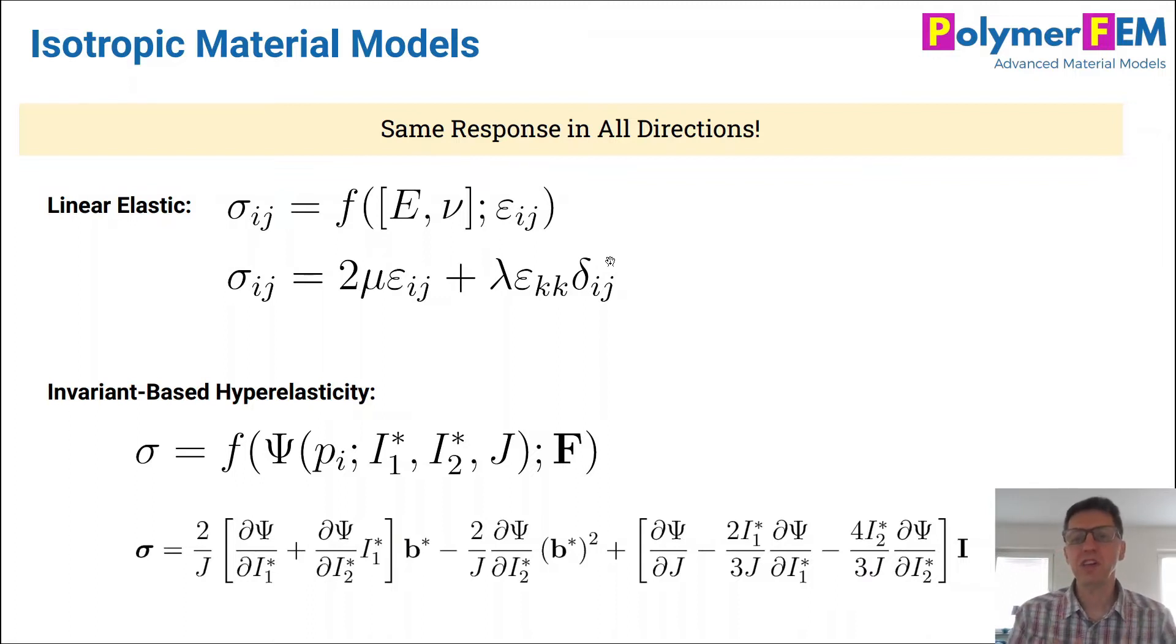But hyperelasticity, which is an extension of linear elasticity, is applicable for larger strains and it's typically written in a very different form. The stress becomes a function of the strain energy function, so it's a function of a function, and then also the invariants of that deformation and the deformation gradient itself. If you want to express the stress more explicitly when you have these types of invariants I1, I2 and J, you end up with this equation down here. I've talked about that in some of my other videos.